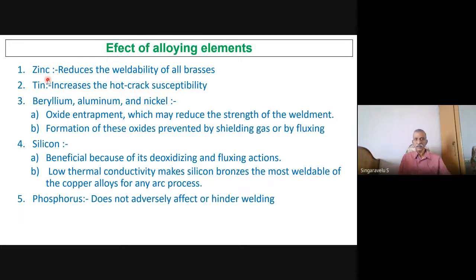Zinc reduces the weldability. Tin increases the hot cracking. Beryllium, aluminium, nickel, all those things: oxide gets entrapped, which reduces the strength of the weldment. Okay, formation of these oxides is prevented by shielding gas or by fluxing. Silicon is beneficial, a deoxidizer, similar to steel. Low thermal conductivity makes silicon bronzes the most weldable copper alloy by arc welding process.